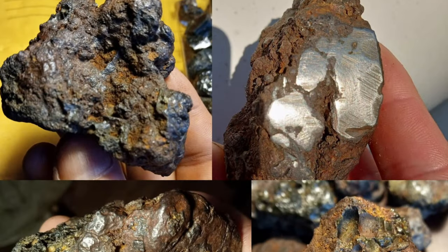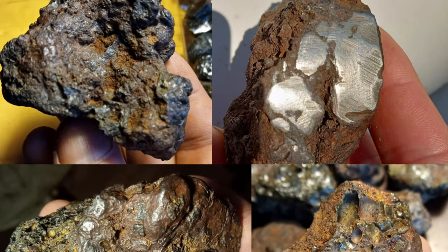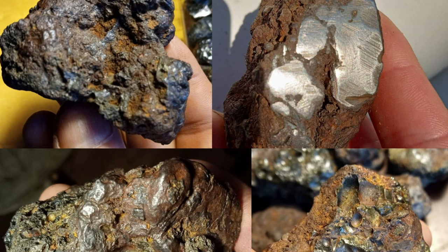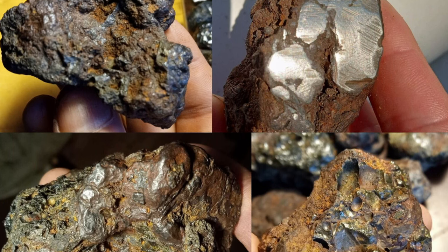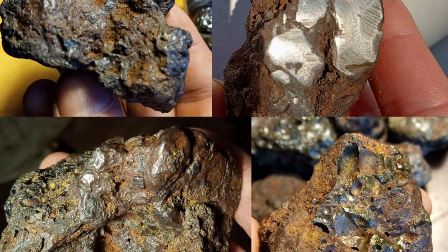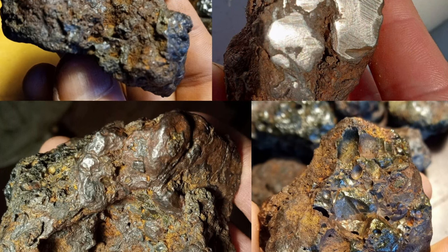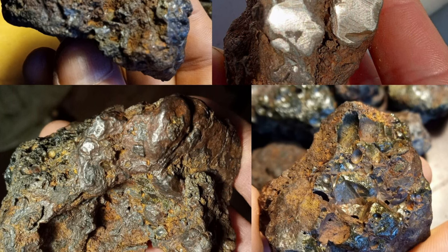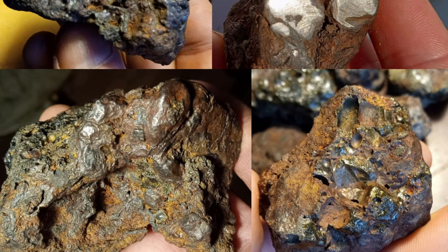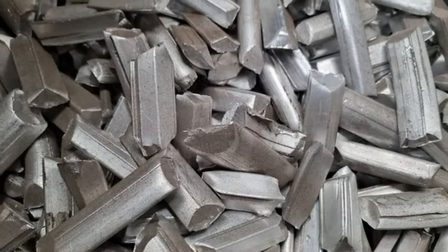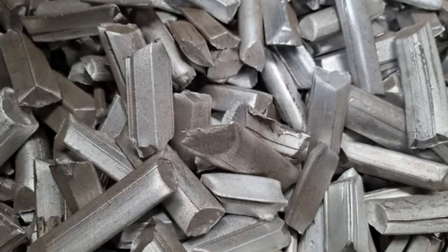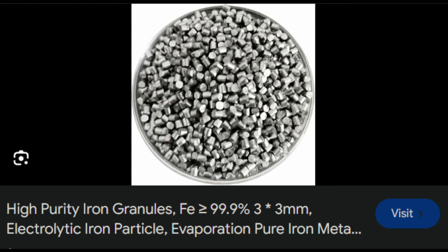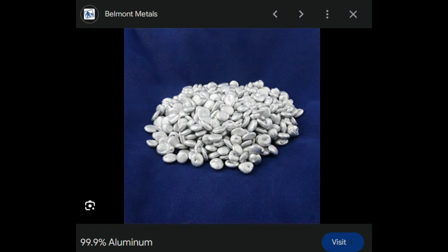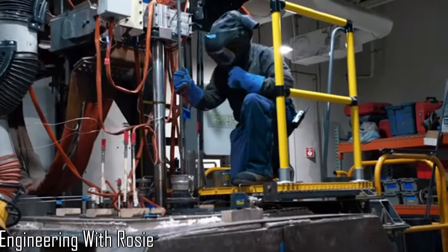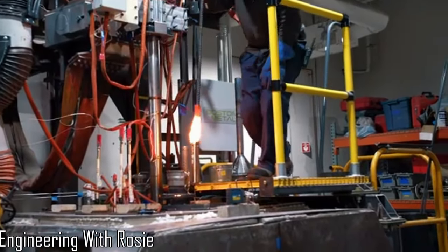But in our situation, we are left with a crappy random alloy created from a bunch of crappy random bonding with crappy random ratios after too many crappy drinks and crappy bars and clubs, and once the heat of the moment is gone, all we're left with is a bunch of gas and a brittle metallic loaf of an alloy. In order to make decent steel or aluminum, we need the metals to be nearly pure. 99% iron, 99% aluminum, and then we can control the amount of alloying metals we add.